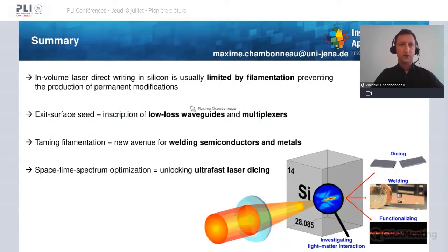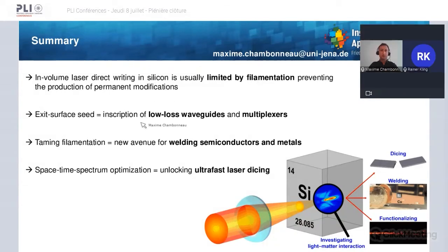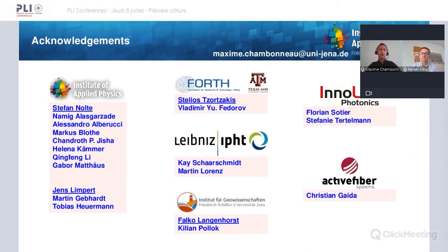So to summarize, in-volume laser direct writing is usually limited by filamentation, which prevents the production of permanent modifications. But you can bypass these limitations by using exit surface seeded inscription for low-loss waveguide writing as well as multiplexers. By taming filamentation inside silicon, it offers a new avenue for welding semiconductors to metals. And with a space-time spectrum optimization, it is possible to unlock ultrafast laser dicing.